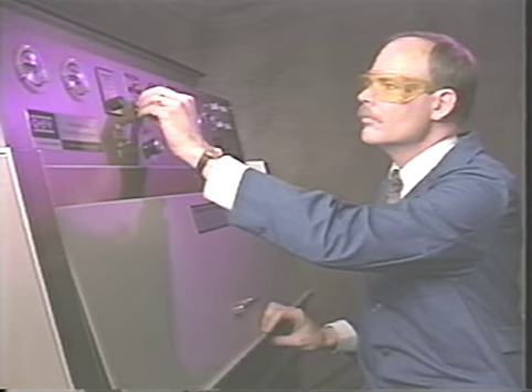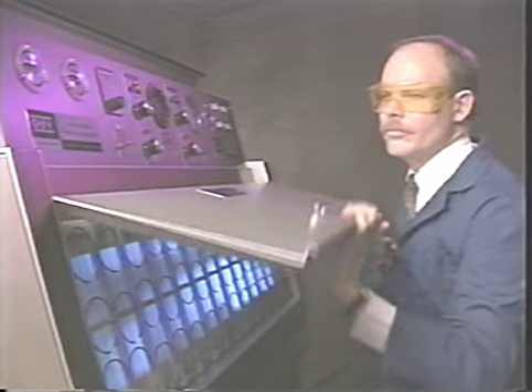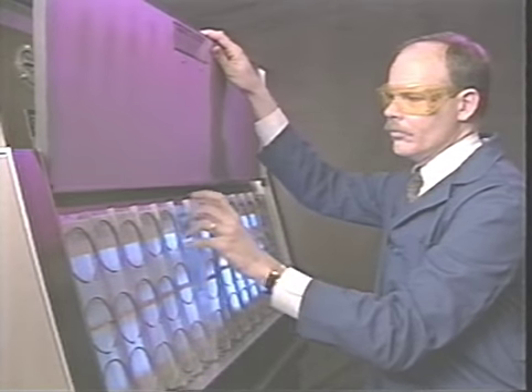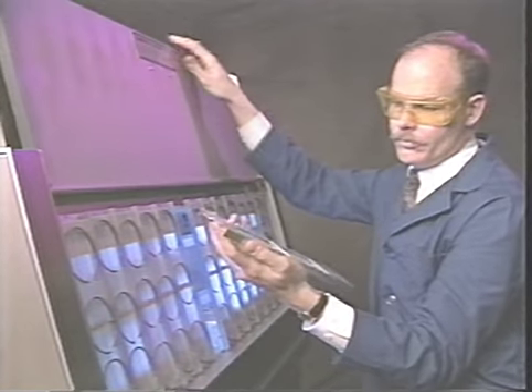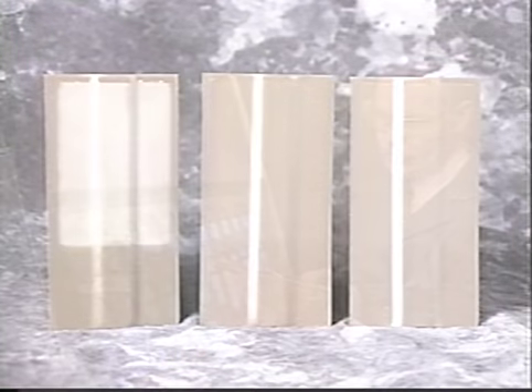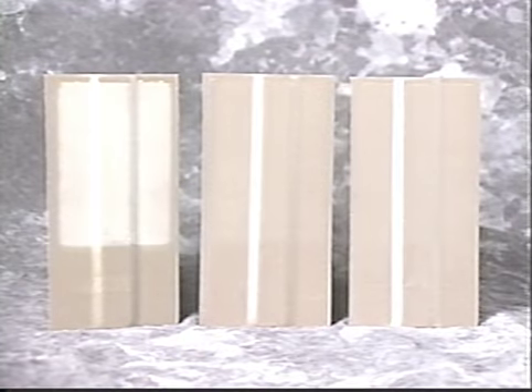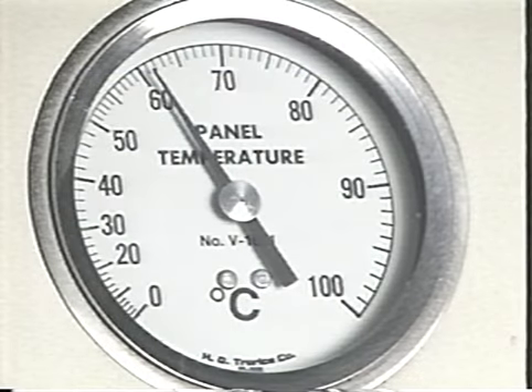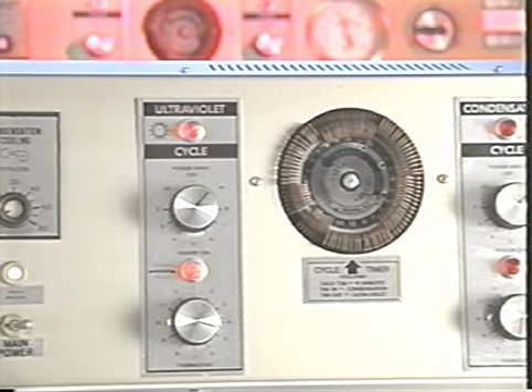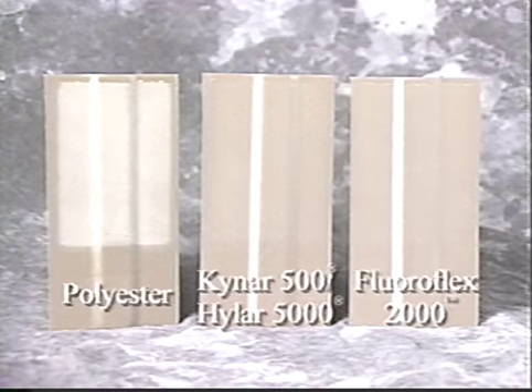Kynar 500 Hylar 5000 proves its superiority in fade resistance over other paint systems in accelerated weathering tests. These samples have been exposed to alternating 4-hour periods of ultraviolet B light that simulates aggressive sunshine and condensation that simulates dew and rainfall. Our test also included the element of heat, which accelerates the harsh effects of sunshine and moisture. As you can see, the sample on the left has changed considerably where the polyester paint film has been